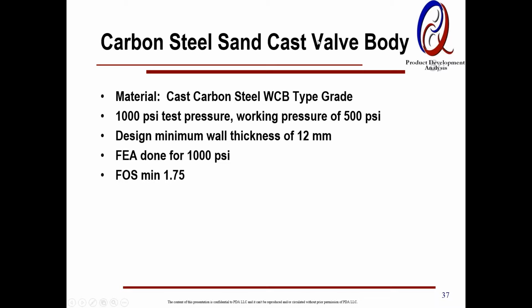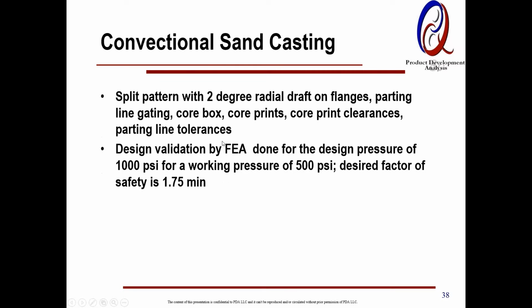Another example is really I want to demonstrate what you can gain with tighter dimensional tolerances. And that's another quick low-hanging fruit. So we looked at a carbon steel cast valve body, WCB, 1000 PSI test, working pressure 500, minimum wall thickness 12 millimeter, which was derived based on the ASME code and FEA.